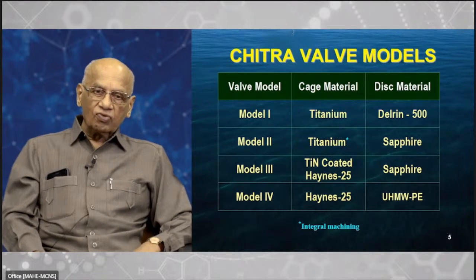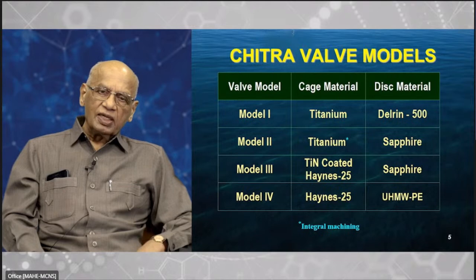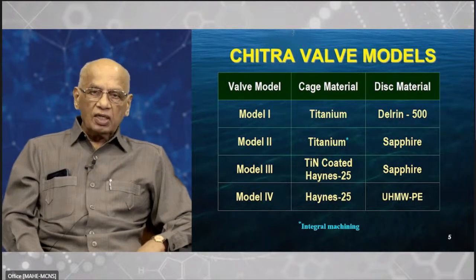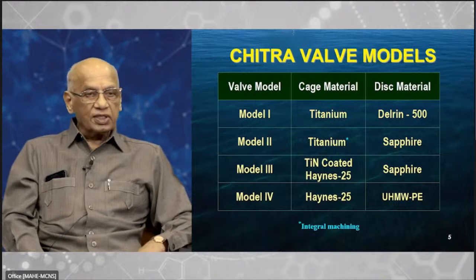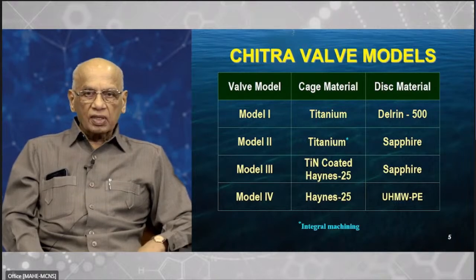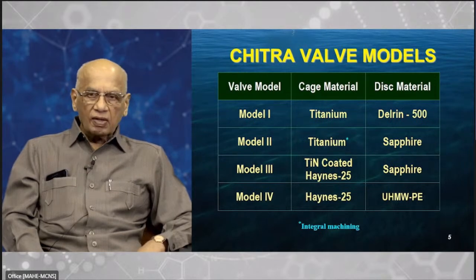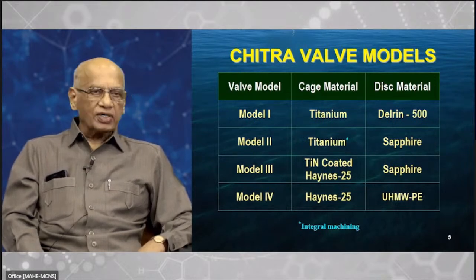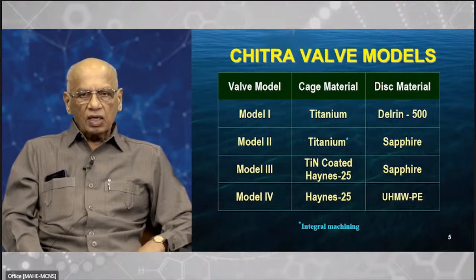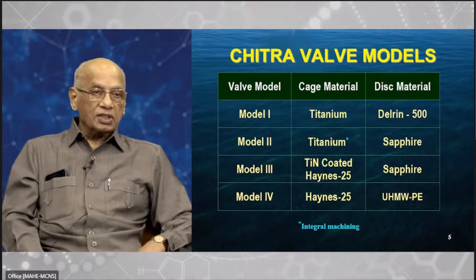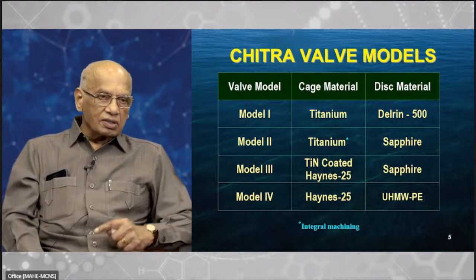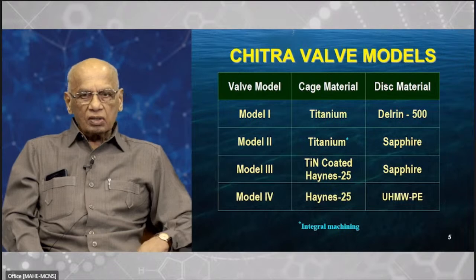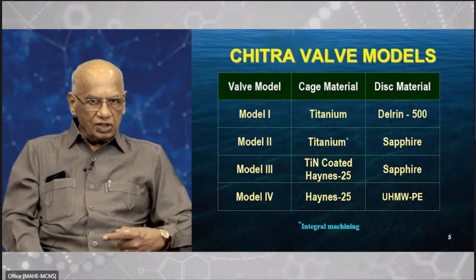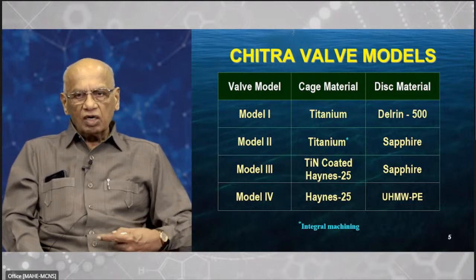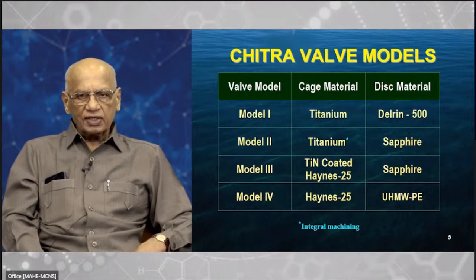Now these are the 4 models. The model, the picture I showed in the beginning, that's the 4th model which is successful, which has been used from 1990. In model 1, our cage material was titanium, and the disc material was DELRIN 500, made by DuPont. Model 2 was titanium, but the cage initially, the struts which you saw, they were electron beam welded. In this case, it was an integral cage. We will see this later. And the disc material we changed to sapphire, synthetic sapphire.